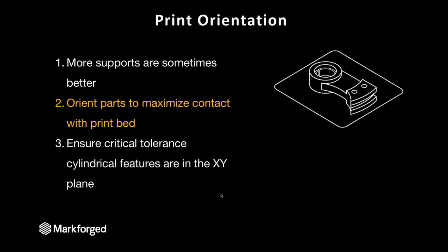Another important thing is print orientation. Sometimes more supports are better, but you also want to make sure that your part has contact with the print bed. Again, if you have a tall, skinny part, it may warp during sintering, so you have to be cautious when you're printing funky geometries. You want to make sure you optimize those parts and have maximum bed contact. And if you do have very critical dimensions, the XY dimensions tend to be a bit more accurate than the Z direction, especially if you're talking about holes that may have some force on them during sintering and may slump a little bit.